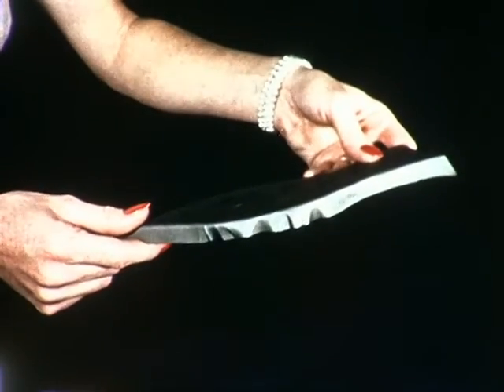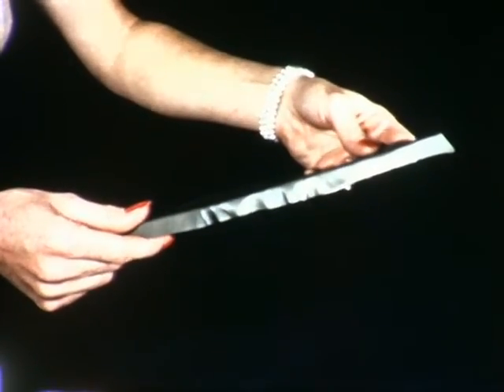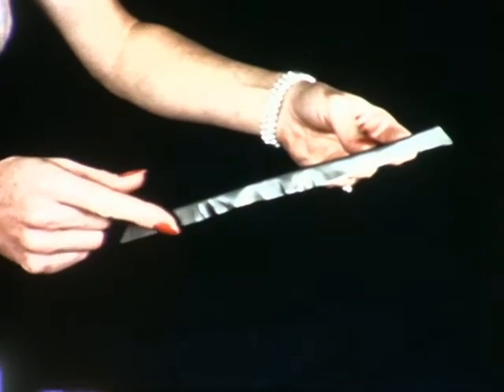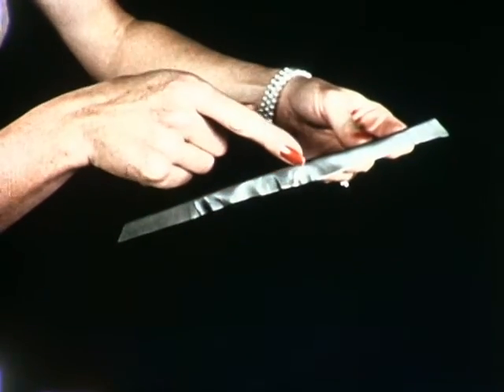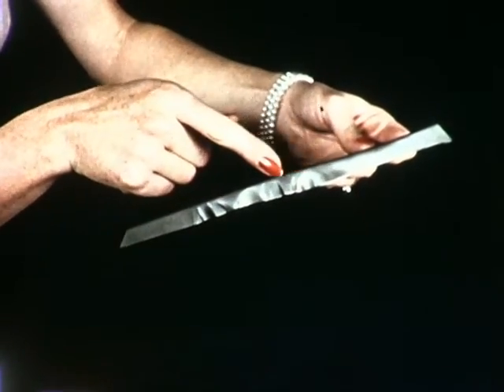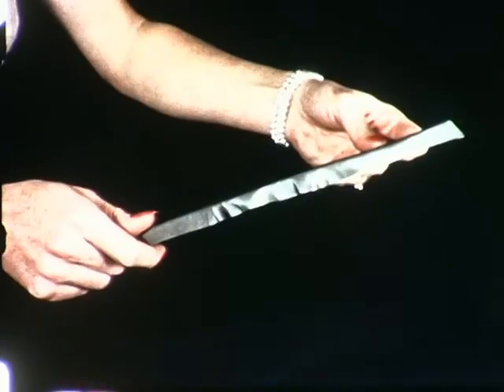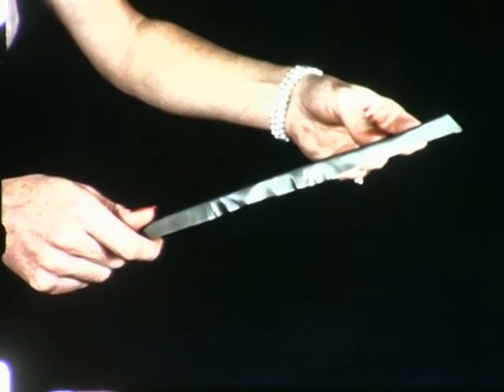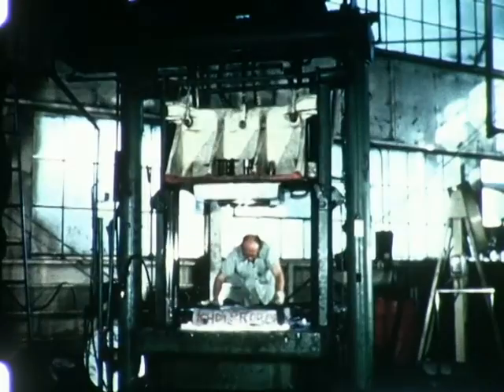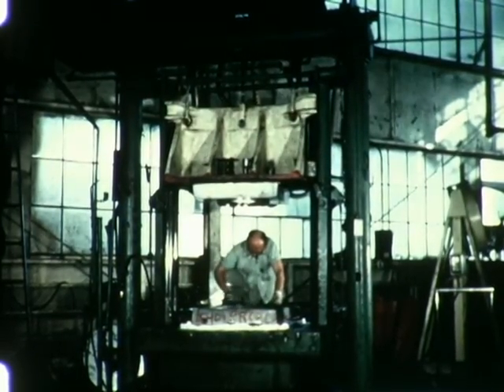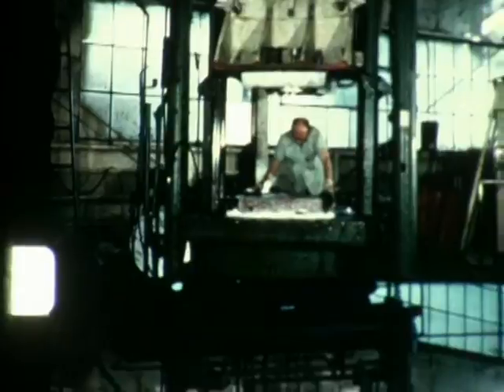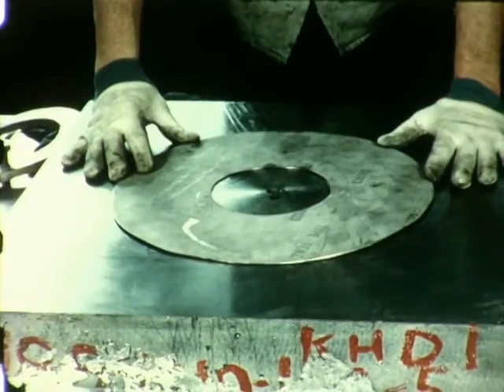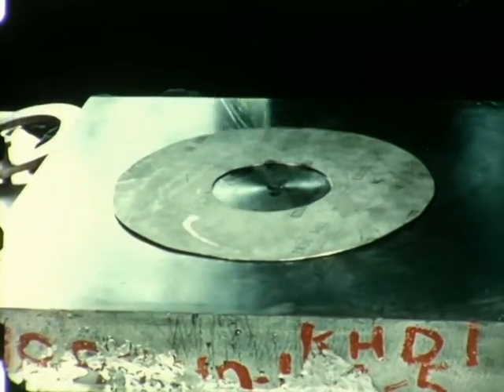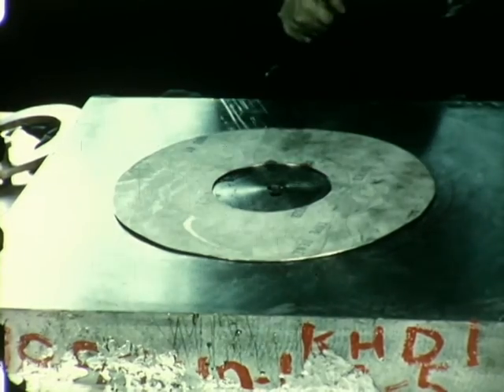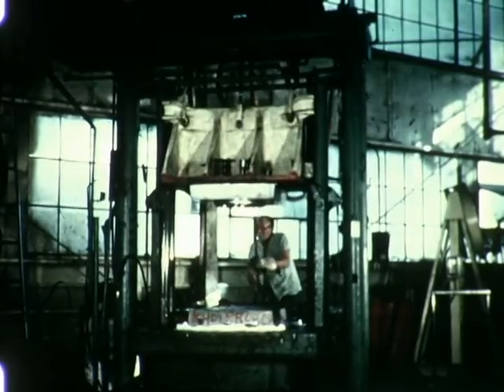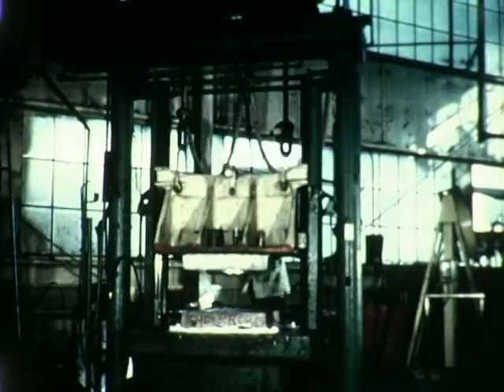Rene 41 does not lend itself to hydroforming, as indicated by this experimental part. It is suggested that forms of this type be made by drop hammer, and straight bends may be brake formed satisfactorily. All material is received in a mill solution annealed state. In this state, sheet metal forming such as bending, braking, and drop hammer cause Rene 41 to form in the same manner as 18/8 stainless steel.